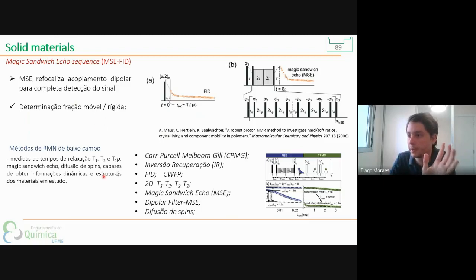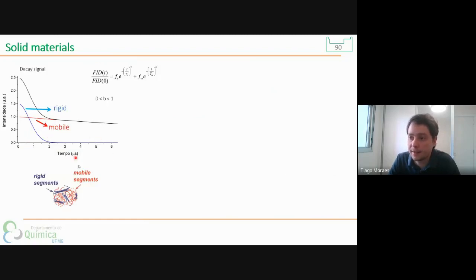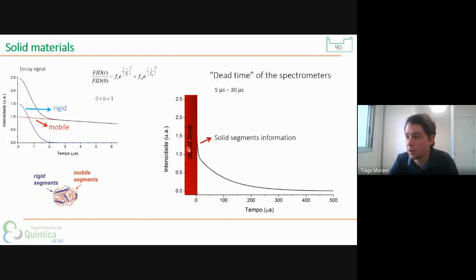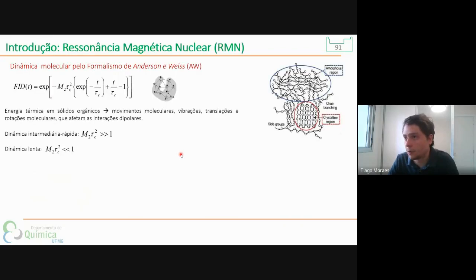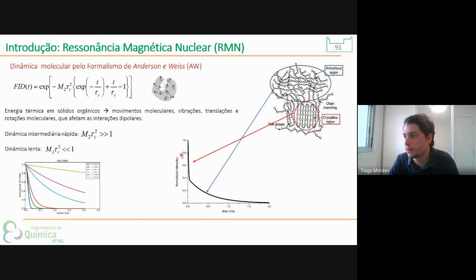This is important, sorry about it. But the idea is just to show that the pulse sequence needs to change to obtain the real information that we want. The information from the rigid parts was being lost. So how do we obtain this information that was in the dead time? We have some models for it, but the important thing is that at the end, we obtain all the information from the mobile, amorphous region, and the rigid parts, and we can quantify how much of each we have.